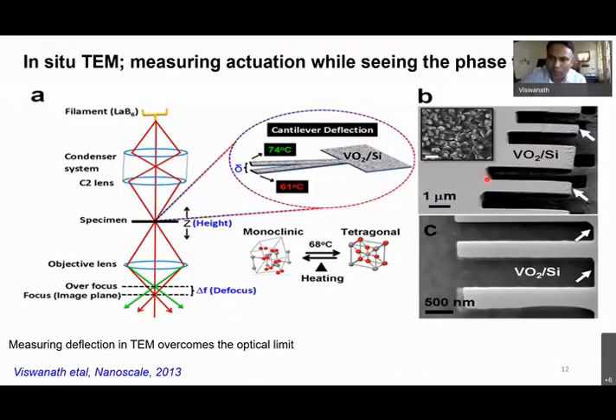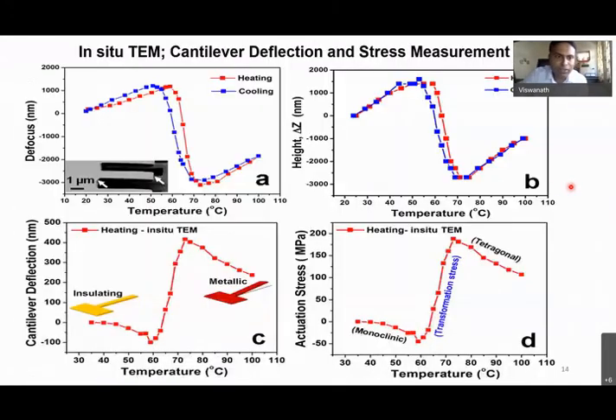Yes, exactly. That's a good point. So we are trying to repeat the experiment. One measurement from the tip, doing the same defocus as a function of temperature that I showed here, and one from the base, where the cantilever is clamped. Whatever curvature change is there because of the thin film deposition can be normalized. Only the difference in defocus value at each temperature between the tip and the base will give you the final cantilever deflection. Okay, that's okay.